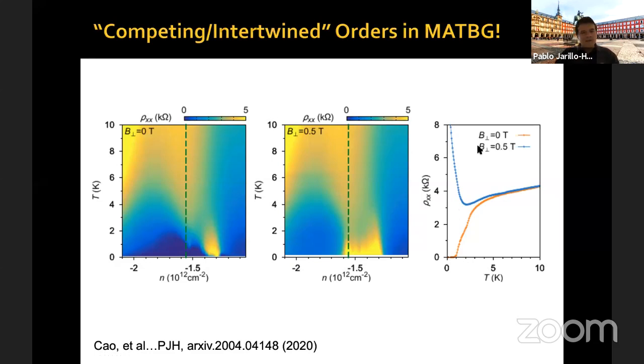Now, at the beginning, if you see this only once, then who knows what this could be due to, but of course, we have now started to see it in more and more devices. This is another device with a twist angle of about 1.07 degrees. This phenomenology happens to be a little bit narrower in angular range than just the observation of superconductivity. We see it typically at 1.07 plus or minus 0.03 degrees or so, the same angular range as indicated here.